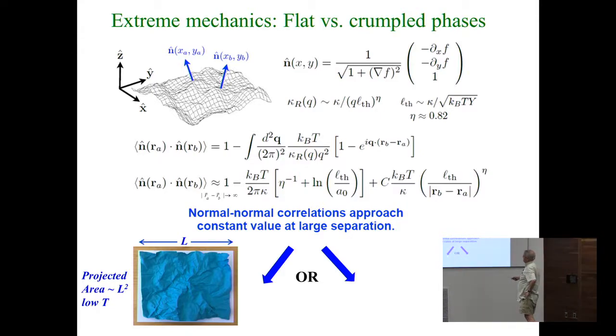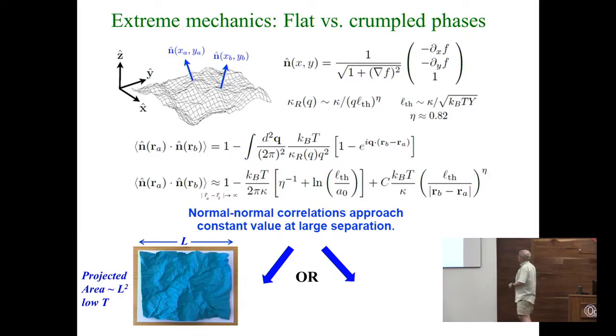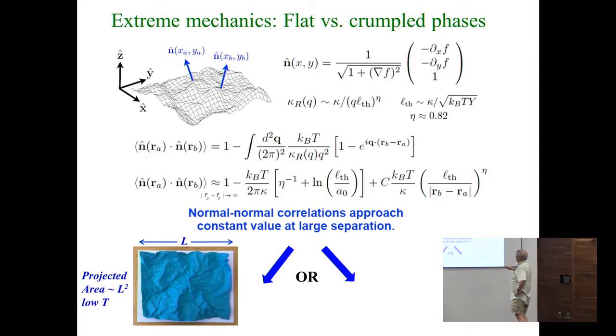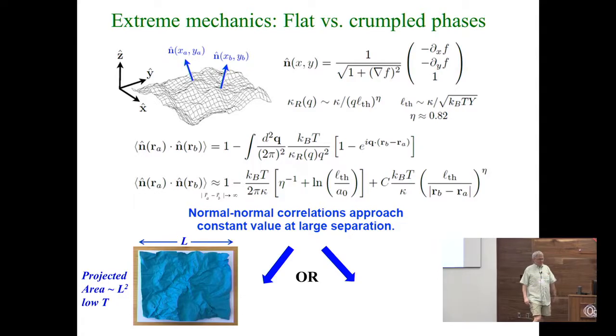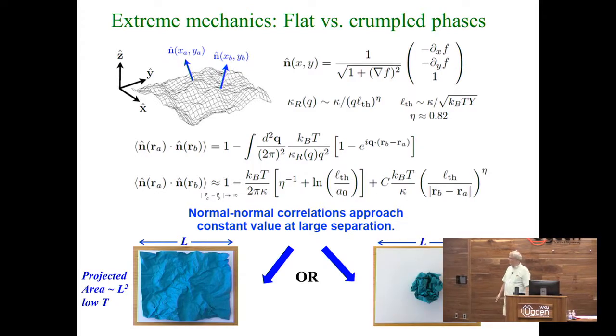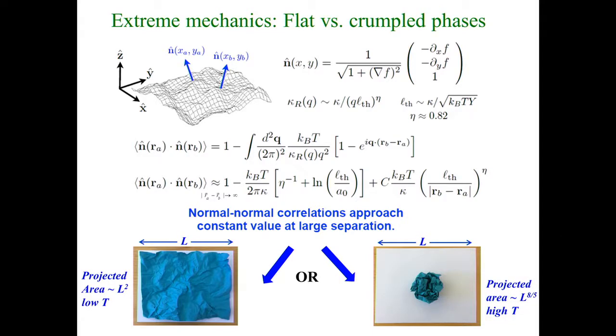And in this flat phase, I have wrinkles, to be sure, but there's still a projected area that goes like the overall size of the graphene sheet squared. But suppose the temperature is high enough, eta is of order 1, this logarithm is of order 1, so high enough so that kBT is of order 2 pi kappa, then this could go negative in principle, according to this calculation. That can't happen. There's something strange going on, and that, you might argue, is a crumpling transition, an indicator of where the crumpling transition would occur.